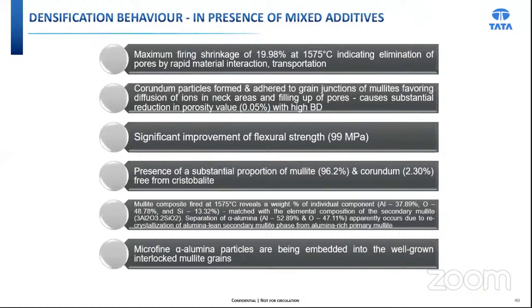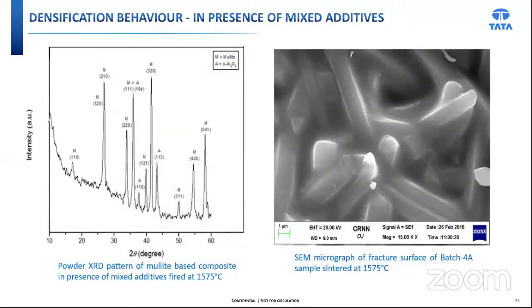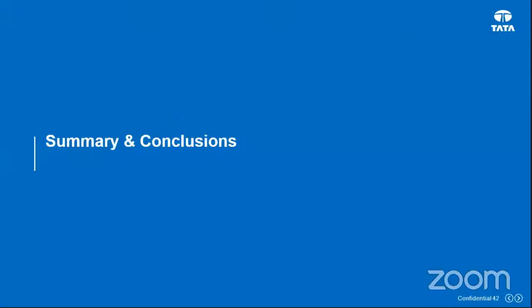Corundum particles formed and adhere to the grain junction of mullite, favoring diffusion of ions in neck areas and filling up of pores, causing substantial reduction in porosity value, that is 0.05%, with high BD. Significant improvement of flexural strength, 99 megapascal, and presence of substantial proportion of mullite, that is 96.2%, and corundum 2.30%, free from cristobalite. This is observed. This is the XRD pattern and the micrograph of the fired compacts with the mixed additives.